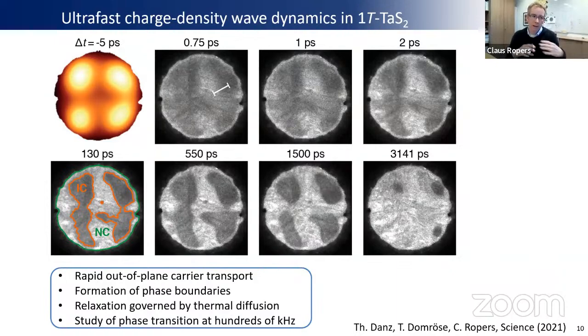But then, depending on the local strength of the excitation, you're either above the threshold or below the threshold, such that there's a back relaxation in regions which are weaker excited, and above threshold excitation actually switches this phase transformation in these hotspots here, and you get a phase separation essentially between those two regions. And already at about 2 picoseconds, you already start to have these phase boundaries formed.